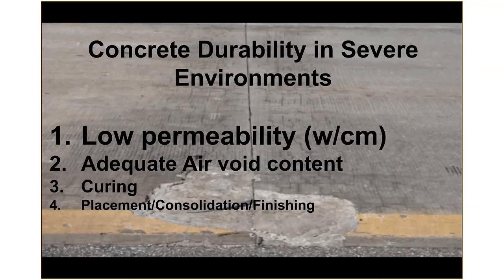protects the concrete. When you entrain an air void system into the concrete, and we're talking 6 or 7% little bubbles, they need to be fine enough and spaced close enough together to produce freeze-thaw resistant concrete. And in theory, when the concrete paste is saturated with water and a frost wave moves into the concrete, the water freezes into the void, and thereby releasing that 9% expansion of water when it freezes, relieves that pressure on the concrete. The concrete does not crack. And as the concrete freezes, capillary action and the surface tension of water pulls the water back out of the void space and into the paste, and you're ready for the next freeze-thaw cycle.